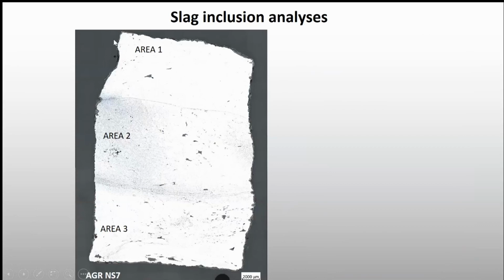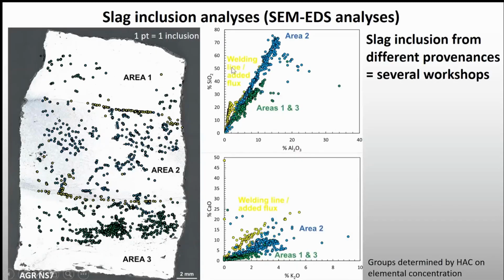So for example, on this sample that we have seen already with the welding lines, you see there's slag inclusion everywhere, and the first thing we do with SEM is to map the entire surface to analyze all the slag inclusion. And so here you have some of the results of the analysis with colors which correspond to compositional groups, which are determined on the different concentrations of some of the elements, such as alumina, silica,